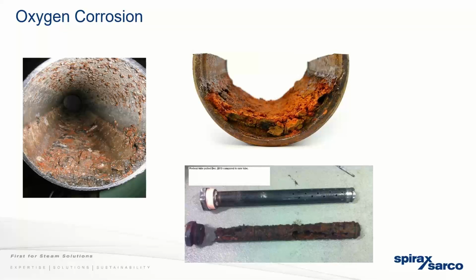You can also see the ones below, the picture with the two sparge tubes, and you can see what the new sparge tube looks like and what one of the really corroded sparge tubes looks like as well. And that is actually sitting in a feed water tank. Most of the time it's sitting in most likely a feed water tank. And you can see feed water tank does have oxygen and it will eat those away. Most of the time, that's why sparge tubes or any steam injectors are all made of stainless steel. Okay.